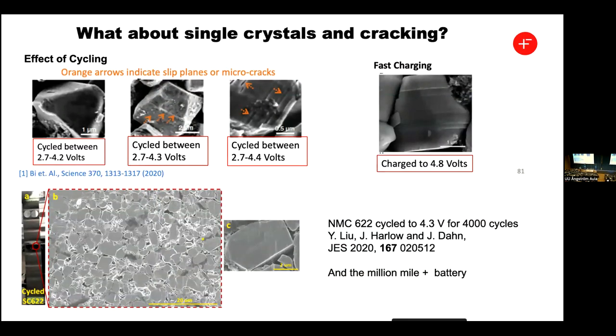And of course, Jeff Dahn's work has really inspired a lot of this work in the community by showing that you could get millions of miles if you went to a single crystal. And he and now others have shown these lovely cross-sectional images that show after multiple cycles, there's really very little evidence in a single crystal of cracking. Yet there are other reports in the literature that do show failure mechanisms of single crystals, and particularly these slippage type events of the particles that are driven at high voltages and also at fast charging.